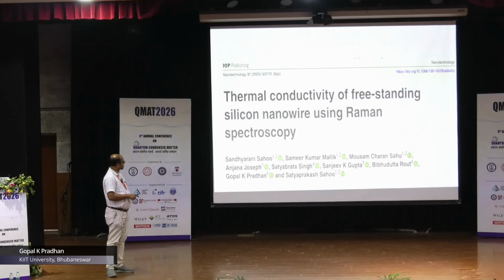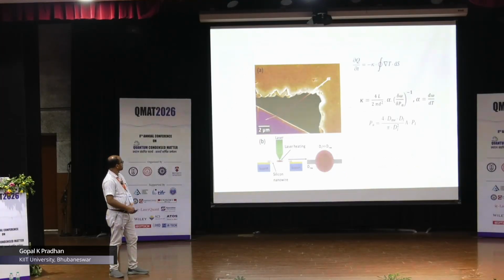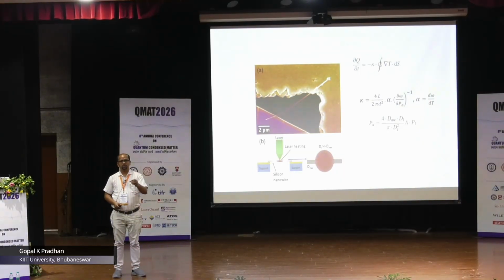This is something that we did, I think, in 2020, where we measured the thermal conductivity of silicon nanowires, but today's talk is on two-dimensional materials, so I will see how we extend this to other systems. This is basically a freestanding nanowire, and this is what you do from the diffusion equation. This is the modeling. What I want to draw your attention to is this d omega by dT, the temperature coefficient of the Raman shift, and this d omega by dP, the power coefficient of the Raman shift, and there are other quantities like the length and the diameter for this system. And you calculate effectively what part of the laser is being used to heat up your system, though not the entire laser beam is falling onto it.